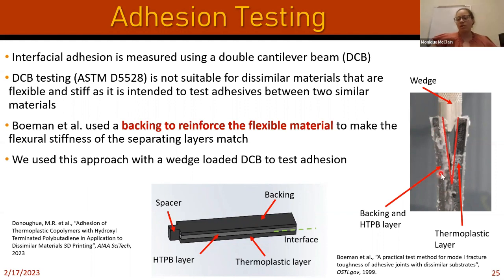The HTPB kind of got everywhere, but here would be the thermoplastic layer. This would be the interface of the HTPB to that thermoplastic layer that's bending apart. And this would be the backing that's helping to reinforce the HTPB as we're splitting it apart. When we made this, we had an initial crack that we had made with some tape, and then we're driving a wedge between the two.